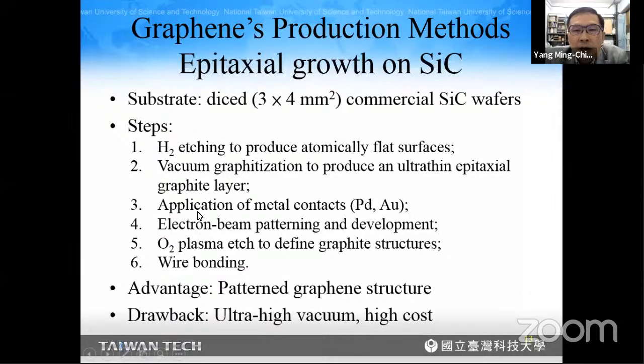And then we apply metal contacts such as palladium and/or gold. And then use an electron beam to pattern the graphite layer. And lastly, follow that with an oxygen plasma etch to define the graphite structure. The advantage of this method is that we can produce a patterned graphene structure. The drawback is we need a high vacuum, ultra high vacuum, and the cost is high.